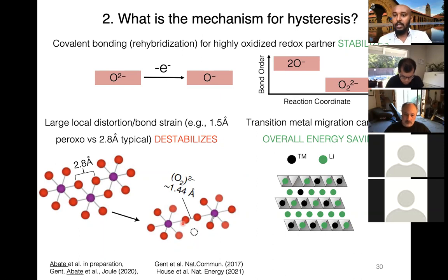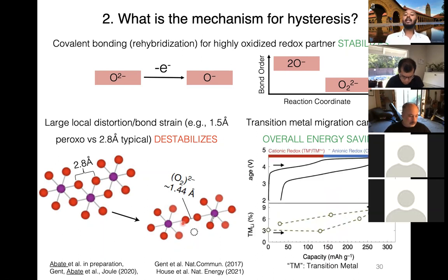We actually confirmed this understanding using experiment, using X-ray diffraction. And here's again the discharge profile of lithium-rich NMC, where the cationic and anionic redox steps are shown. And as you can see, what I'm showing in the bottom curve is the amount of migration as a function of capacity. Here you can see that this amount doesn't change during cationic redox. However, we have a linear change in this quantity as we have anionic redox. Thereby, this could explain why we have this cation disorder to alleviate the bond strain that's created by